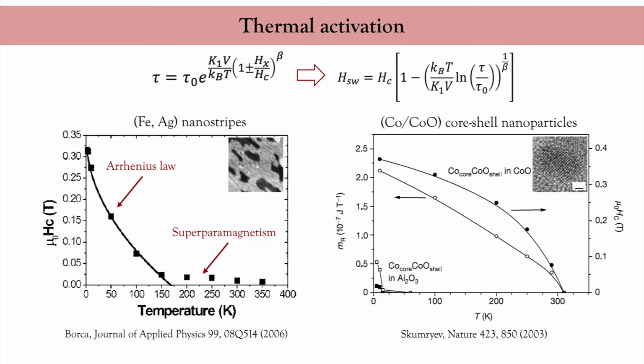If you embed these nanoparticles in a cobalt oxide matrix, a dramatic change occurs. The cobalt oxide matrix is antiferromagnetic, so it exerts exchange bias on the cobalt nanoparticles. This exchange bias enhances the anisotropy energy of the nanoparticles and pushes the superparamagnetic limit up to room temperature.